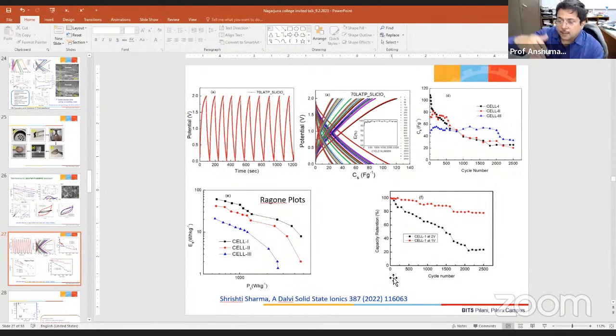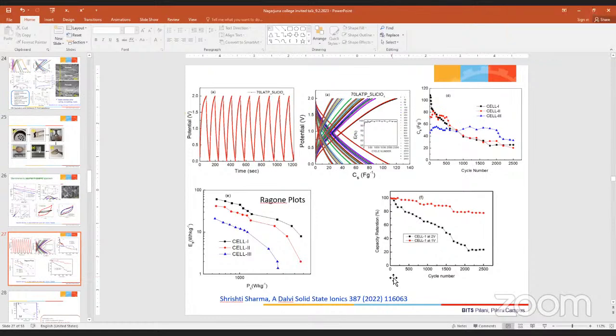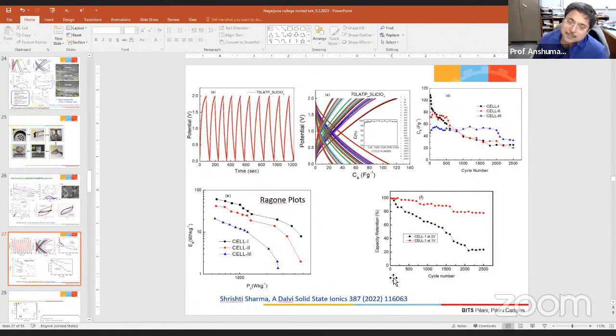If you draw it, now this solid interface still plays an important role here. So if you draw a large current, then there is a polarization effect which happens there. This is a nature, right? We have to understand the nature. A solid interface will always have some kind of polarization, because when ions try to cross the interface or play some role at the interface, if they are moving very fast, then they will polarize and they will have their own electric field. And that is something which should be seen.